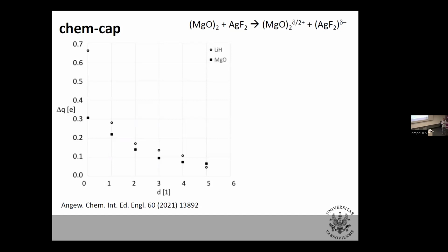One thing is we can control charge transfer between oxidizer and reducing agent in a manner that does not lead to an integer number of electrons exchanged. That's something new. But one will say, okay, but you just showed us the cases where, for example, you take cobalt-O2, you dope with lithium, and you also do this. This is definitely true, but what's the difference?